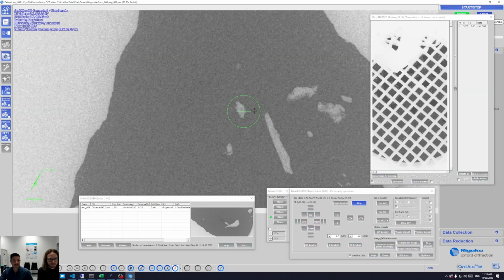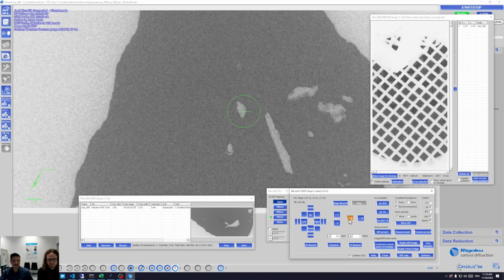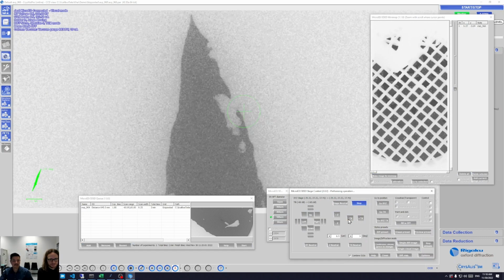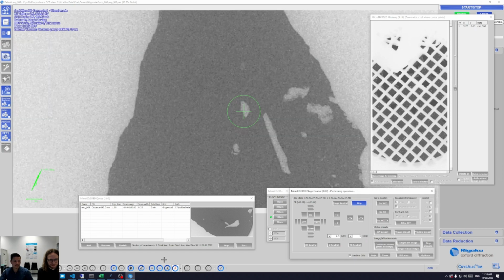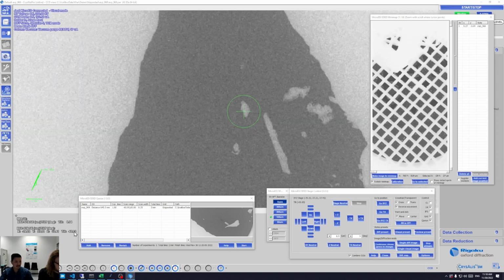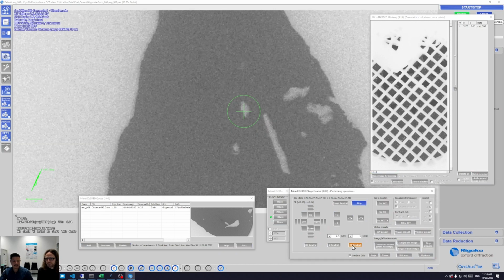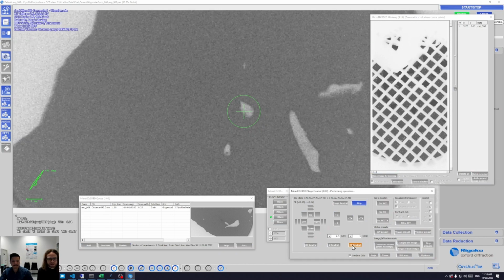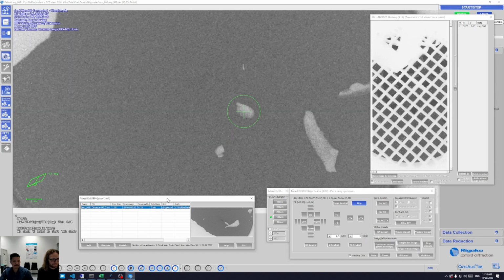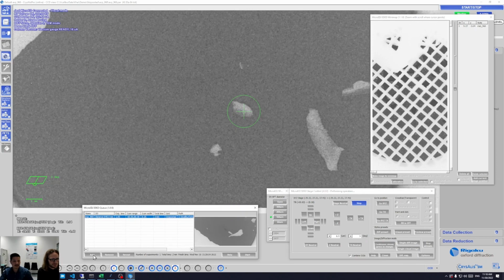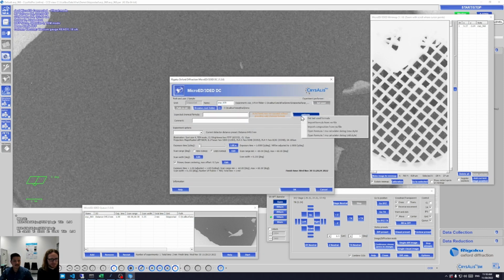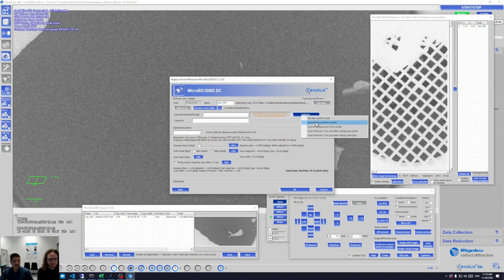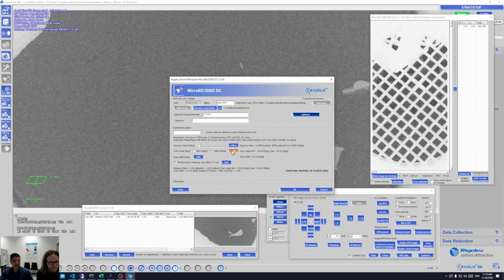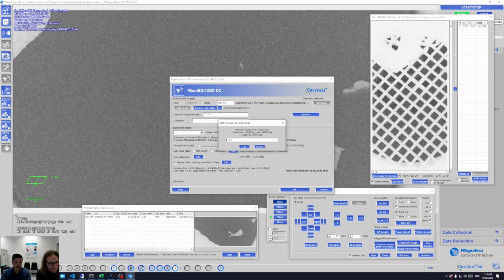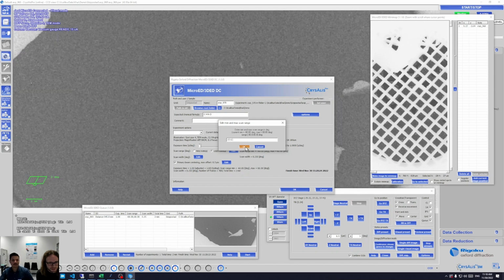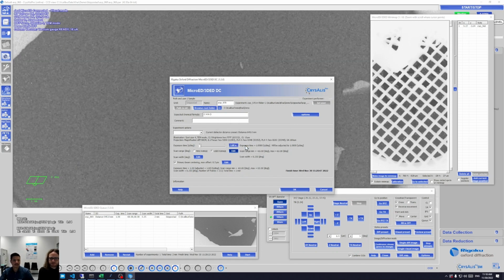It remains in this circle, which means it's just good enough. Also, I want to push it a bit further. No, we're even at 65 degrees. So we could actually, for this grain, even increase the tilt range a bit. And in this queuing feature, you can set the tilt range, and you can actually get the last used formula, you don't have to retype it every time. And for this one, Kai has found -65 to 63 is possible.